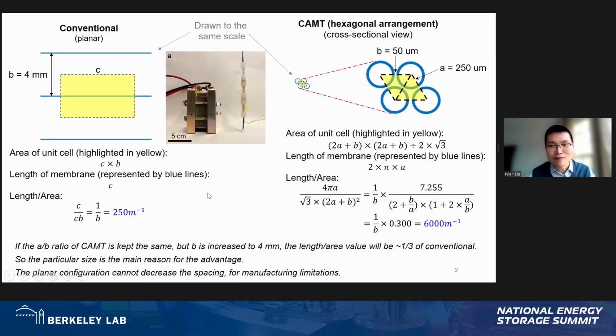So the reason for this boost of volumetric power density is coming from the small size of the membrane. And so you can place the membrane at a distance that's 100 times smaller than the conventional one. So this gives you theoretically 20 to 30 times increase in the volumetric current density or the volumetric power density. And this can save you a lot of footprint and also cost in making the cell of the flow battery.